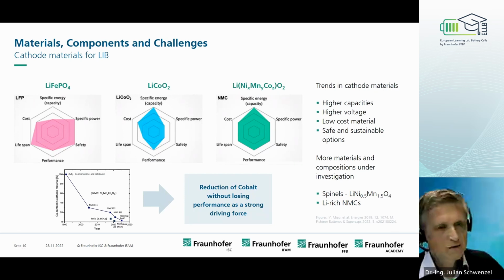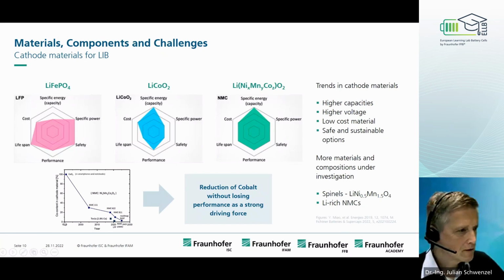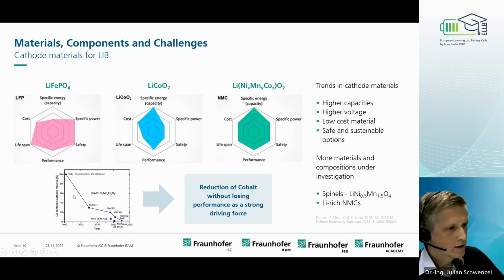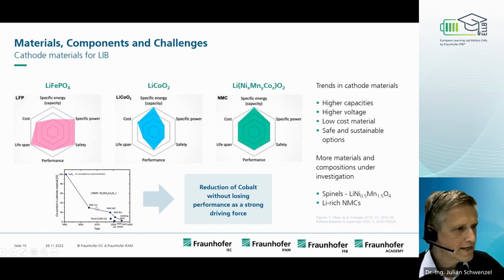So for this, the developments are going in the direction of how we can reduce the amount of cobalt. As you know, cobalt is a very critical material. And here you can see the developments from the last 20 years. The cobalt content in these cobalt oxide-based cathode materials is still going down. And what you can see is this NMC. This means the stoichiometry here, X, Y, Z.